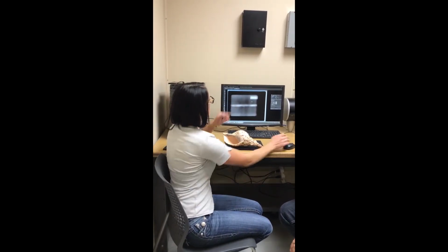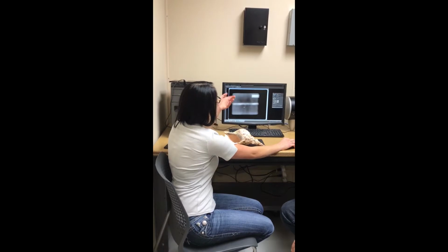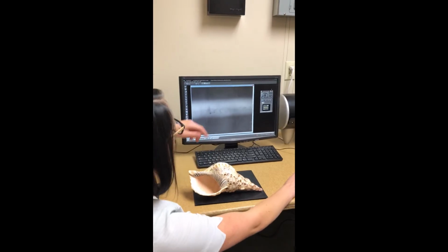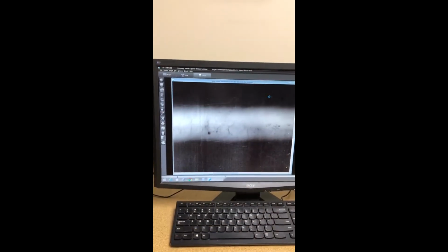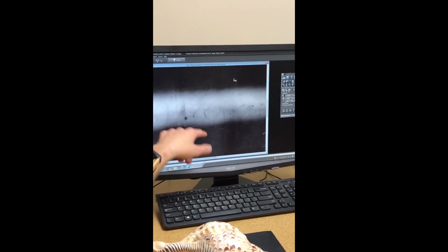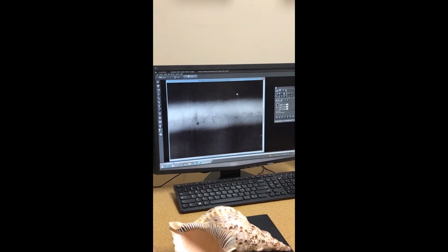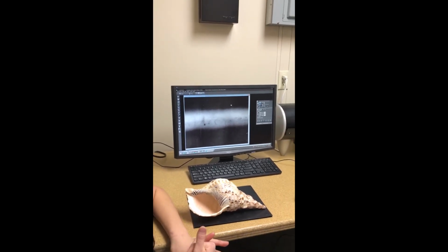This applies to non-destructive inspection, where we can actually take material such as this weld that I photographed here, and we can see the different densities in the material, and using this program I can actually adjust it, and you can see cracks right here that have propagated along the weld, along with some porosity that, if this part was used long term, could be fatal to several lives, which is why it's so important to not only understand what we do here, but understand the impact that it has on people and the world.